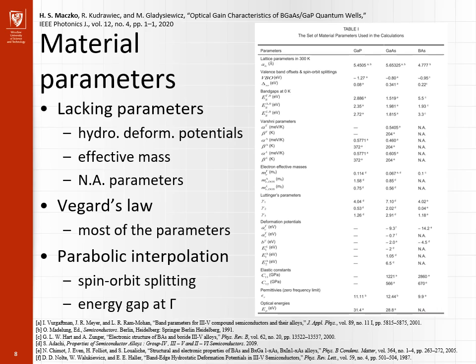Material parameters of the alloy in most cases are calculated based on Vegard's law. The parabolic interpolation is applied only in case of spin-orbit splitting and energy gap at gamma point, since only for these quantities bowing parameters were available.